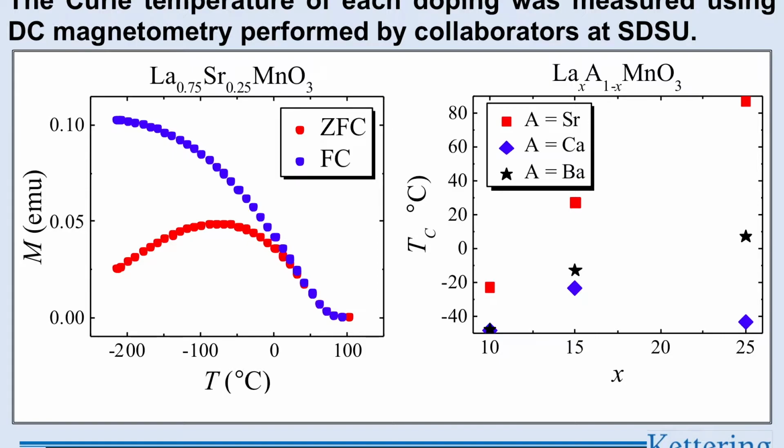But the strontium-doped one is really promising, and we have a fairly linear response of Curie temperature to doping. If we were to draw a line right here, and 45 is that magic temperature, it turns out that around 0.18 to 0.22, or 18 to 22 percent of the lanthanum atoms being replaced by strontium atoms in the structure, is where we would want to be. We've since started making them at that doping, and these things do heat up to a point. I can't show the data yet because we're in the last stages of publishing it. But they will actually shut off and hold at that temperature. So it's very promising in that field.